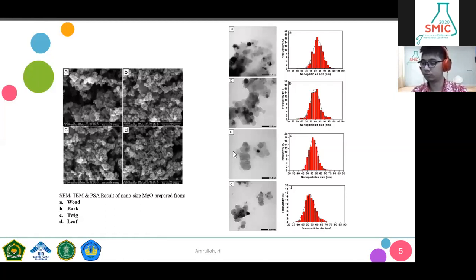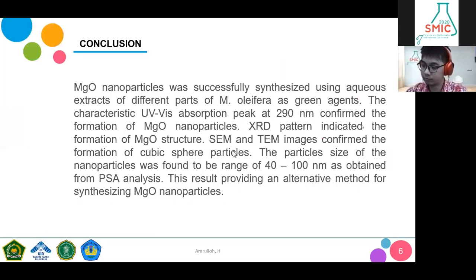Based on the result, magnesium oxide nanoparticles have been successfully produced using aqueous extract of different parts of Moringa oleifera, providing an alternative method for synthesizing magnesium oxide nanoparticles. Based on the result above, it can be concluded that magnesium oxide nanoparticles were successfully synthesized using aqueous extract of different parts of Moringa oleifera